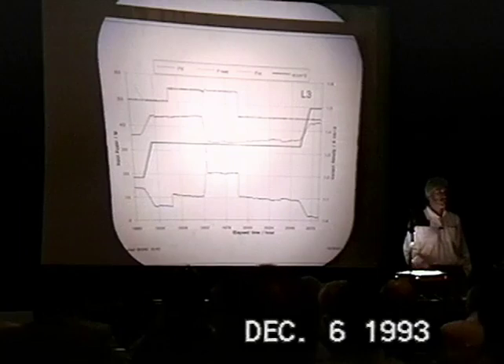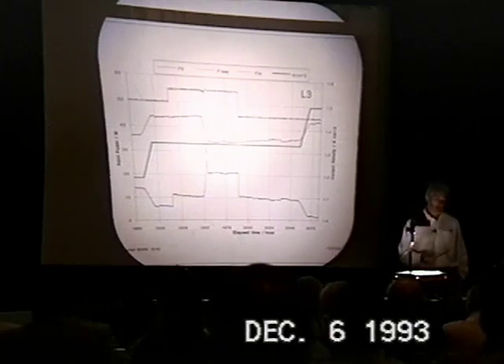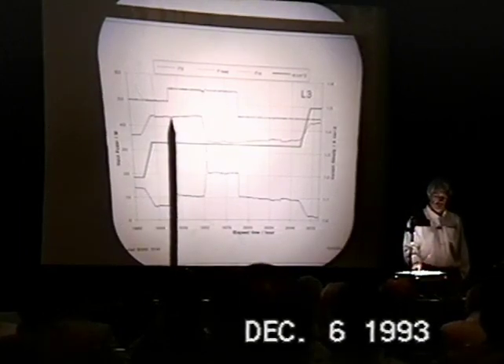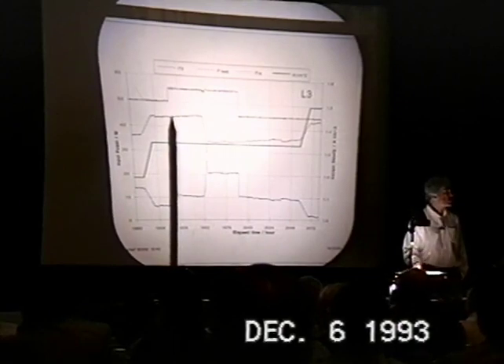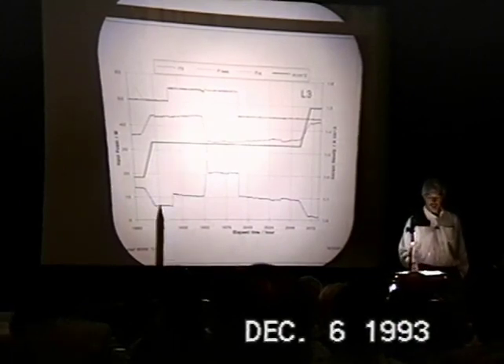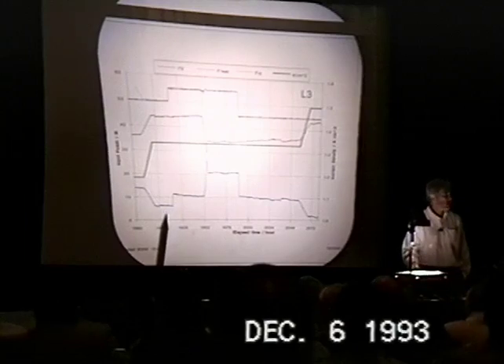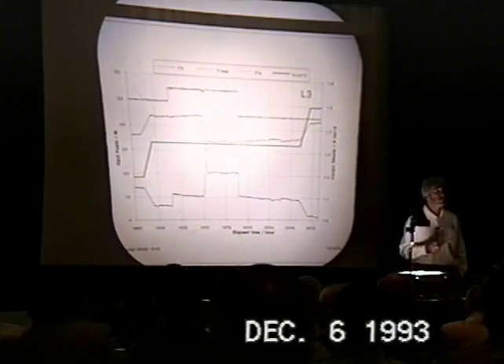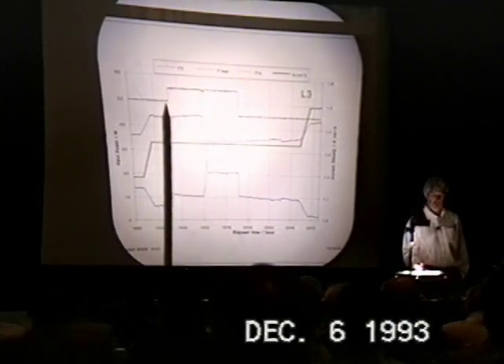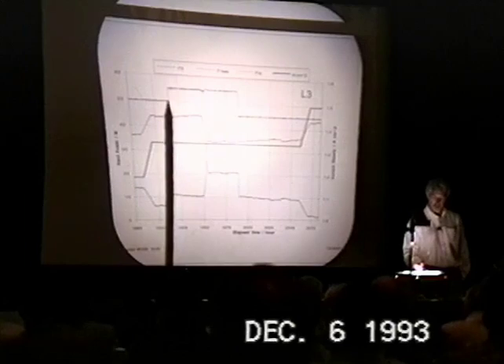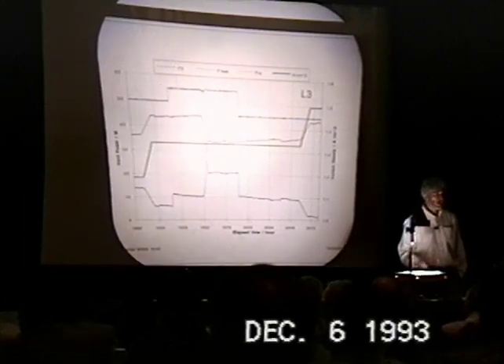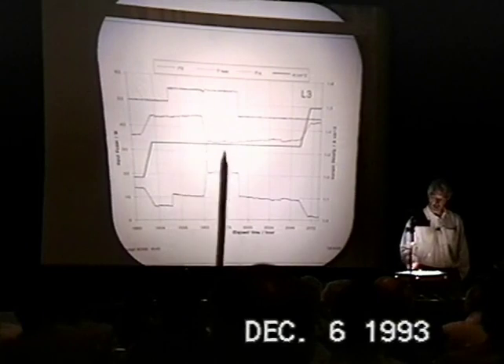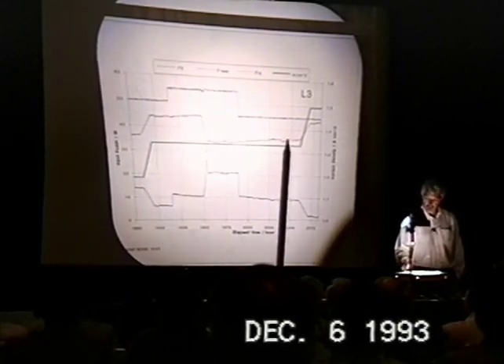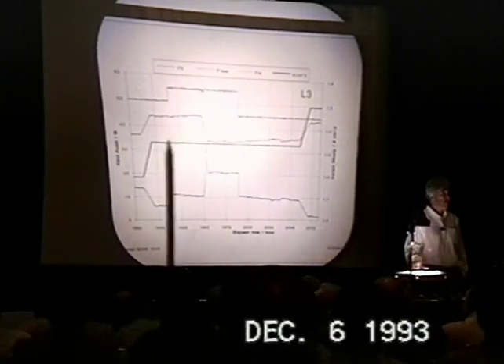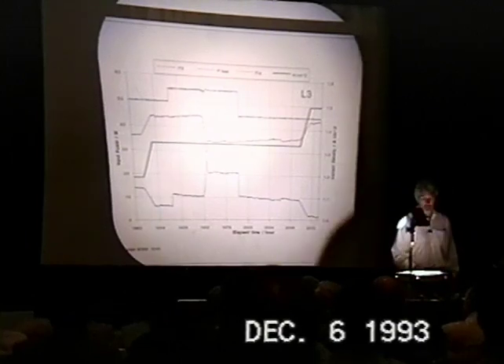We run our calorimeters in what we call a constant power mode, where the computer determines the electrochemical power, here represented by the red line, and adds to it an amount of power in a control heater, here the blue line, such that the sum of them is the control value. At this point, we simply stepped the control value from 50 to 55 watts. A lot of watts, a lot of current density. Here the current density is about 1.35 amps per square centimeter.